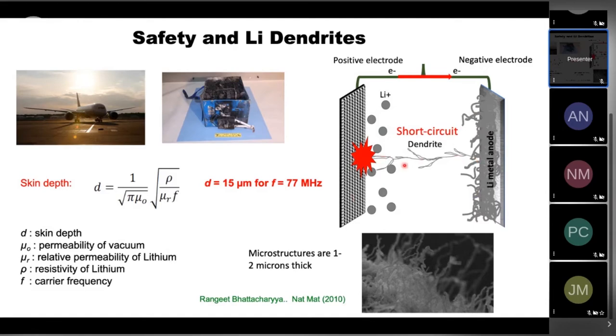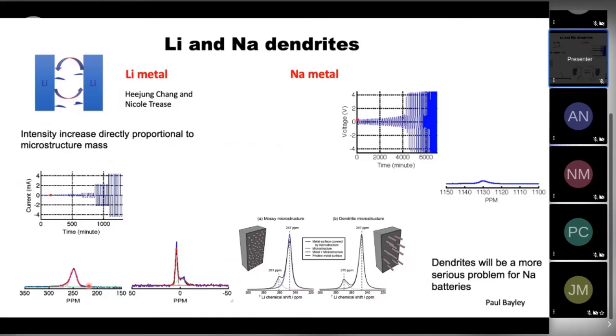Now, what we identified was that NMR, as I mentioned before, when it hits a metal, has a problem of a skin depth. And what that means is that the radio frequency fields can only penetrate a certain amount. And for lithium, it's about 15 microns. And so what that means is you can see the lithium dendrites, but if you look at a lithium metal slab, you can only see about the first 10 to 15 microns. So we came up with a clever way of using that to track dendrite formation. This is a simple example where we're using a so-called symmetric cell, where the lithium is going backwards and forwards. You have a constant amount of lithium and we're increasing the current.